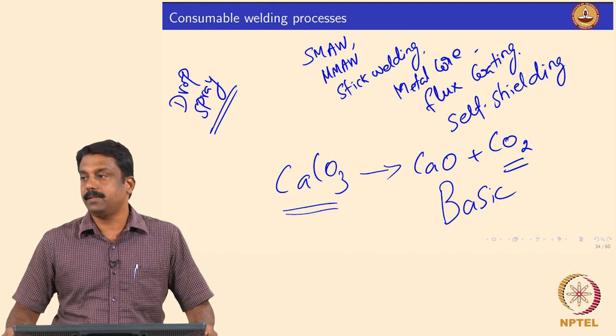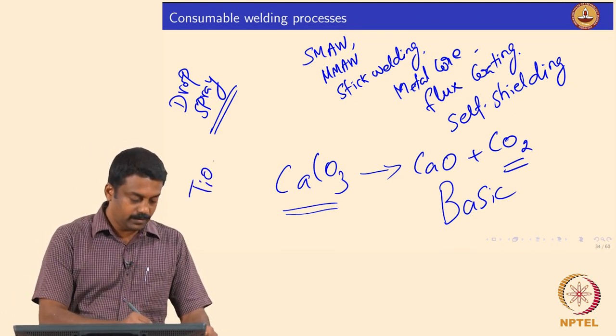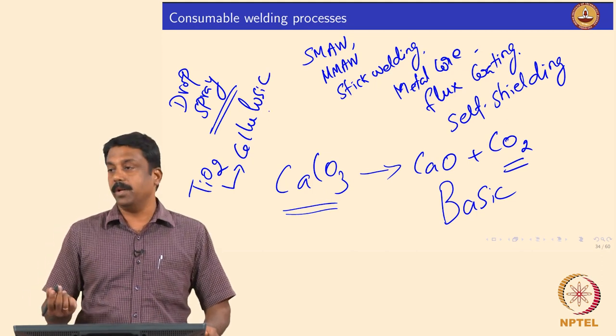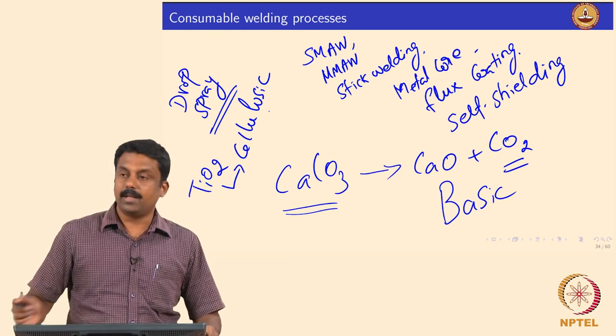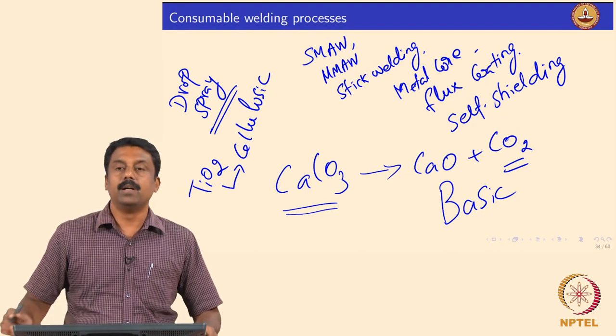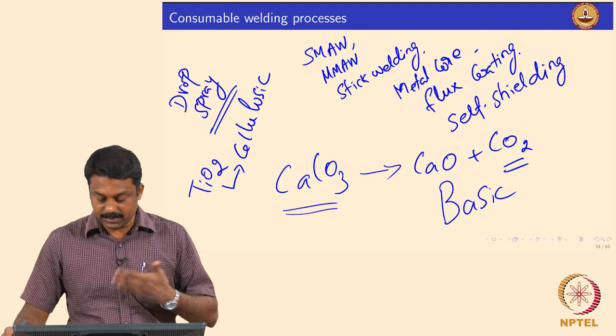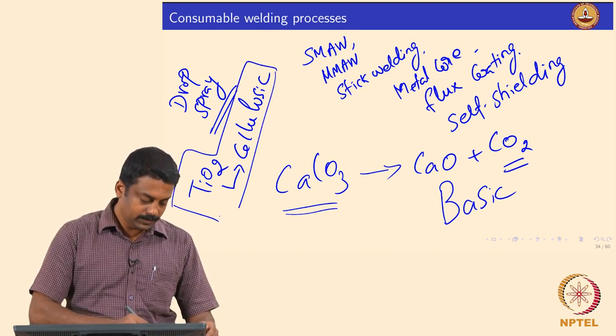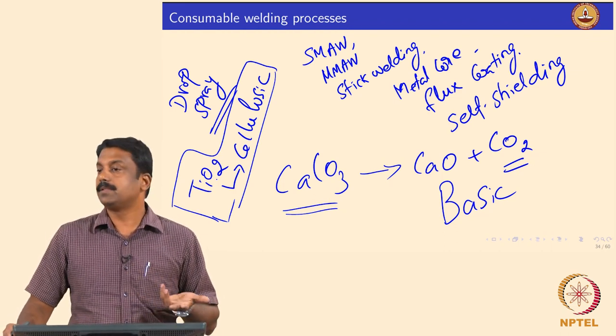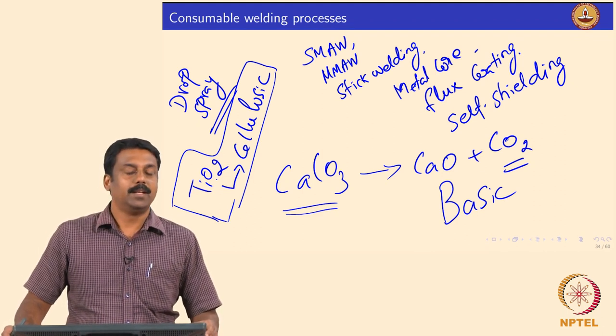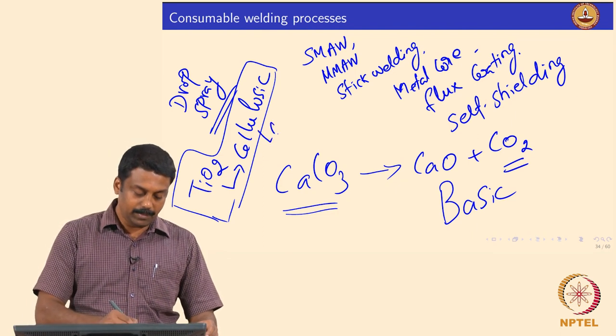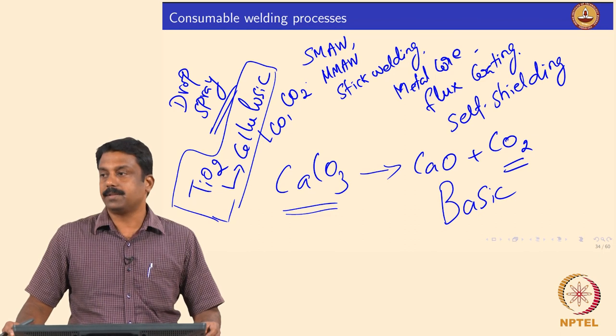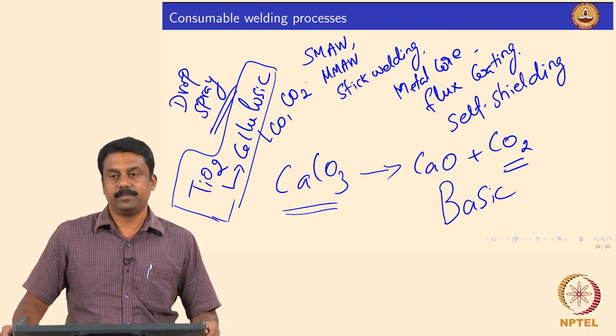You can also have flux made from rutile and some cellulosic material. Cellulosic material is made of wood particles and natural fibres. Cellulosic material can be added to either basic or rutile-based fluxes, most commonly with rutile (titanium oxide) fluxes. When cellulosic material burns, it generates carbon dioxide and carbon monoxide — providing enough CO₂ and CO gases required for arcing and shielding.